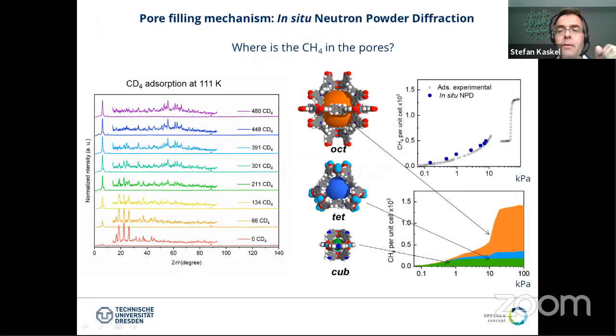So in order to understand and prove that this pore filling mechanism is responsible, we went into in situ neutron diffraction analysis. And neutron diffraction is in particular valuable to locate the guest molecules inside the pores. And we have done CD4 adsorption at the same temperature. So in the neutron diffraction, we have to substitute the hydrogen by deuterons, but the physical properties are quite similar for the CD4. And then we can locate these molecules inside the pores. These are the experimental patterns, which I don't want to describe in detail. But what is shown here is basically the degree of filling with respect to the pressure of the smallest pore, which is the MOP, and then the tetrahedral pore and the large octahedral pore.